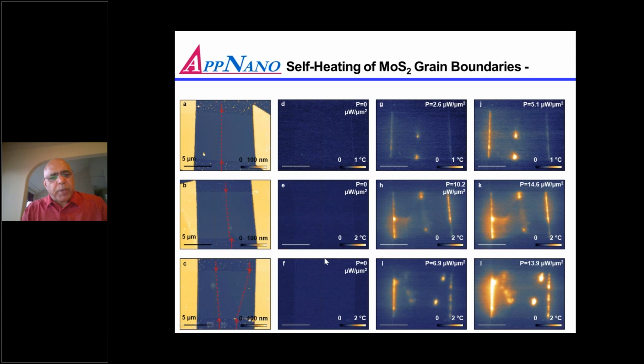grain boundaries especially, and so you can see those grain boundaries. Again, the same way where you have those grains and you are powering them, you get those hot spots, and the temperature change is like, say, 1 to 2 degrees, but the thermocouple probe is so sensitive that you can detect those. And this is just a factor of different powers being fed. So you can see as the power increases, the temperature also increases in these devices. And this is from the Northwestern University group.